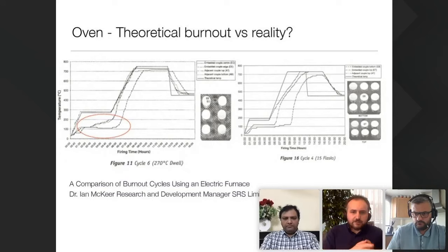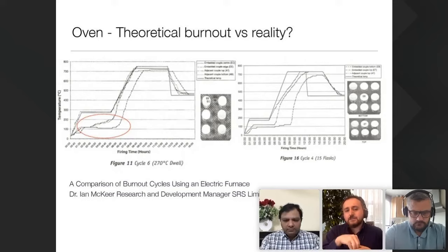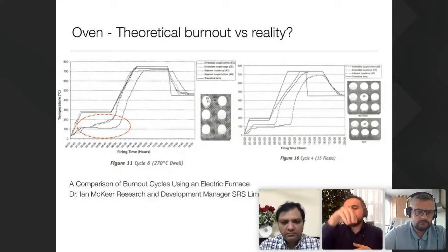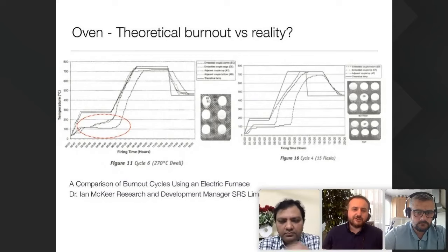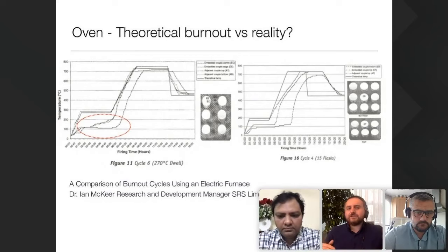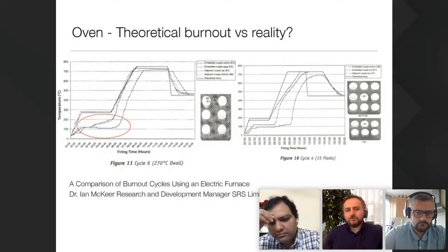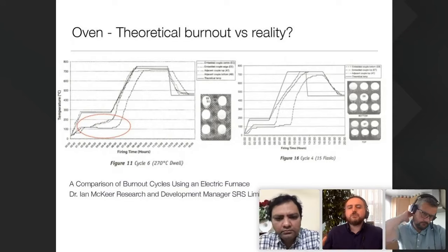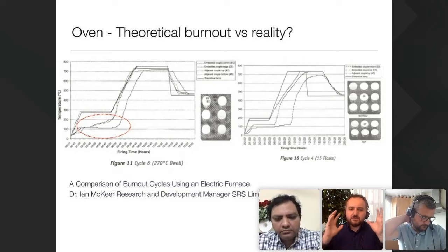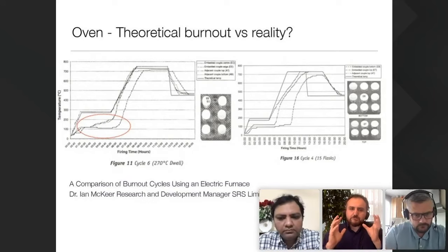What you can see on the left-hand side is the theoretical curve, and on the bottom, the red part, is what's happening inside the flask in two different regions, the bottom of the flask and the middle of the flask. So even if you go to 500 degrees or 270 degrees or whatever temperature you program your oven, what happens is that inside your flask, you have water.